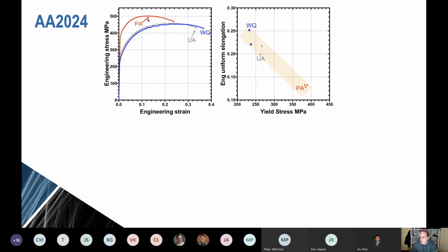And the red curve is the peak aged state. So this is the T6 state. It's been given the heat treatment at elevated temperature that allows it to have the highest strength. You can see a UTS here of about 500, a yield strength of about 380. And then the grey curve is an underaged alloy. So underaged, this is treated for times less than the peak age state. So it will have some precipitates present, but also a lot of solute left in solid solution.